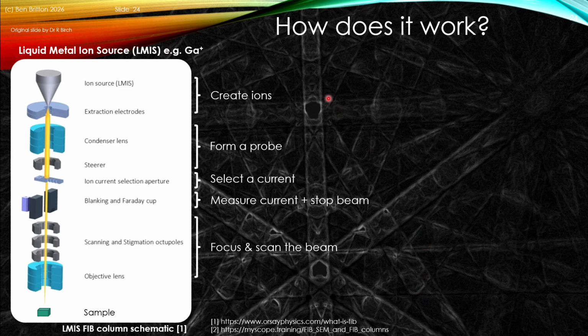Now, the FIB itself, there are two types of flavor typically of FIBs. The first of which, which are typically more established, are the gallium FIBs. These are using a liquid metal ion source. And so in this system, we have a very similar setup where we have the ion source at the top. We then have the ability to extract the ions from the end of the wetted tip. So we have the extraction electrodes that then can accelerate those ions,